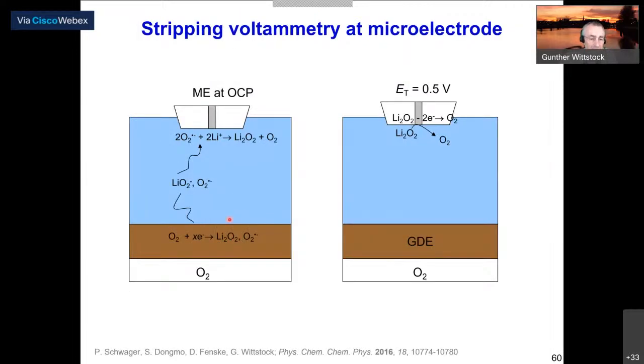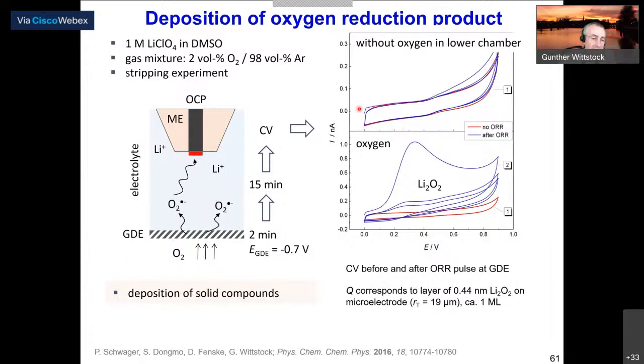And the problem is, again, that we may not have just the formation of peroxide, which is the standard reaction, but that a substantial part of our oxygen may actually form superoxide, or lithium superoxide, which has a certain solubility in the electrolyte and diffuses to the microelectrode. It's then passively collected at the microelectrode, forms a deposit on it, and is then stripped off in the cleaning pulse.